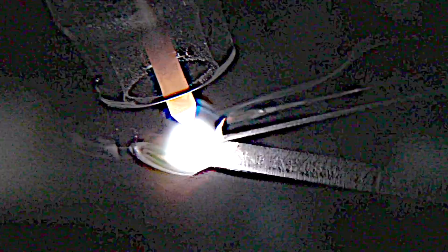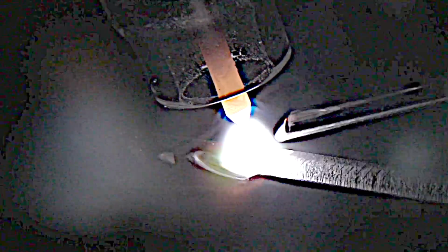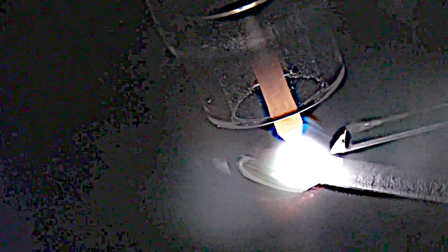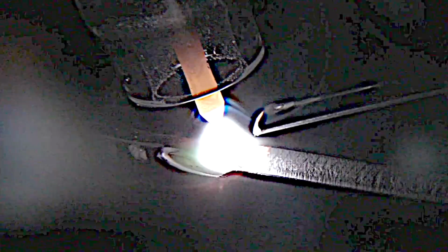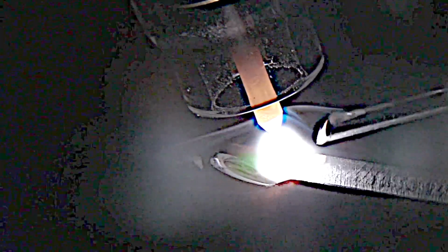Let's take a look right now, though, of a 45 degree tapered tip, 2% lanthanated on an aluminum outside corner joint. This is just about the same taper that I used on that thick steel just a few minutes ago. This is 3/16 inch thick aluminum, so I'm probably up around 170 to 185 amps or so, and it's maintaining that tip just fine.